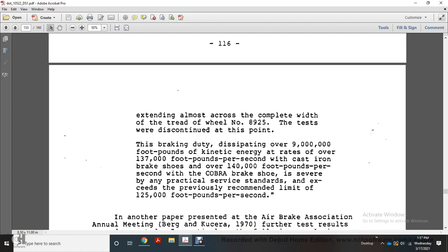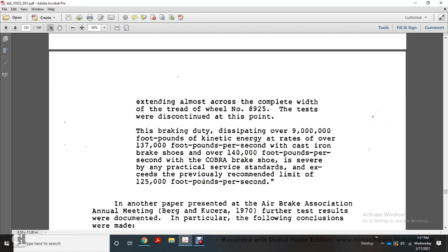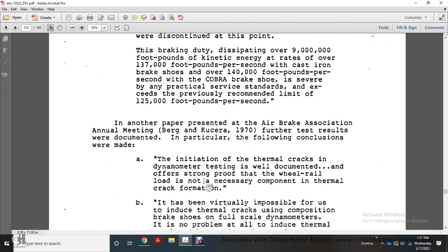The braking duty dissipated 9 million foot-pounds of kinetic energy at a rate of over 137,000 foot-pounds per second with a cast iron brake shoe, and 140,000 foot-pounds per second with a Cobra brake shoe, well beyond any practical service, and the previously recommended limit of 125,000 foot-pounds per second.